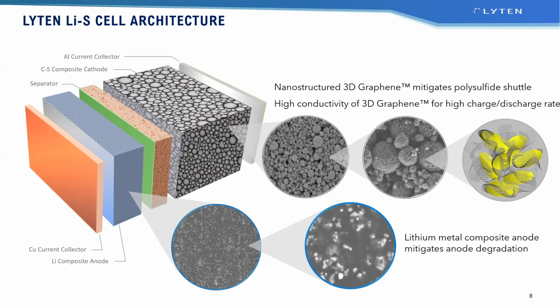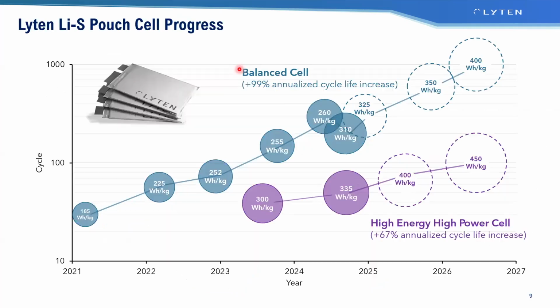People have not done it because lithium metal is a little terrifying to work with. Very few people have the equipment to even look at it. To even look at how the lithium is evolving in the cell, you need a focused ion beam, a FIB SEM. Otherwise, you're doing very empirical things. And if you want to create these alloys, you have to create them yourself, which means melting lithium in a crucible in a glove box, mixing other things in it, and then rolling and extruding that. Most people find that daunting, but we're actually doing it in our facility to develop this. So there's a lot of room to develop lithium anodes to improve cycle life.